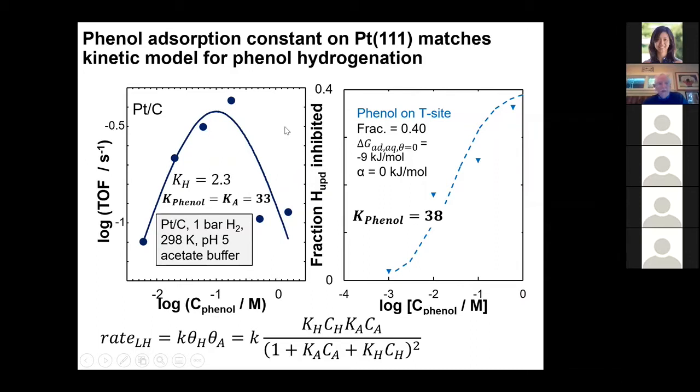In the gas phase, you have to go up to like 200 degrees centigrade to do any catalysis with these organics. Otherwise, they're poisoning the surface. Whereas they happily do catalysis at room temperature in the aqueous phase, and this explains that. So yes, it's a good time to take questions.